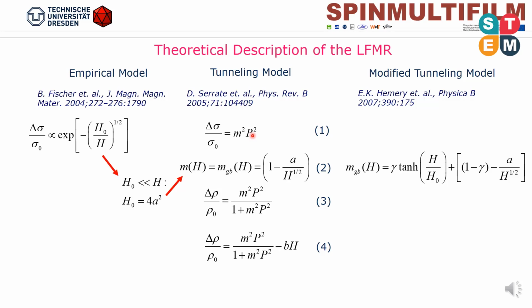On the other hand, the grain surface is a defective double perovskite, whereof the geometry, vacancies, and antisite disorder act as random spin pinning centers, which suppress ferromagnetism. Therefore, the bulk reduced magnetization is replaced by a magnetic field dependent magnetization m sub GB of the region close to the grain boundary, which was taken in the functional form widely used for spin glasses possessing a weak anisotropy, equation 2. Rewriting the first equation in terms of magnetoresistivity, we arrive at equation 3.